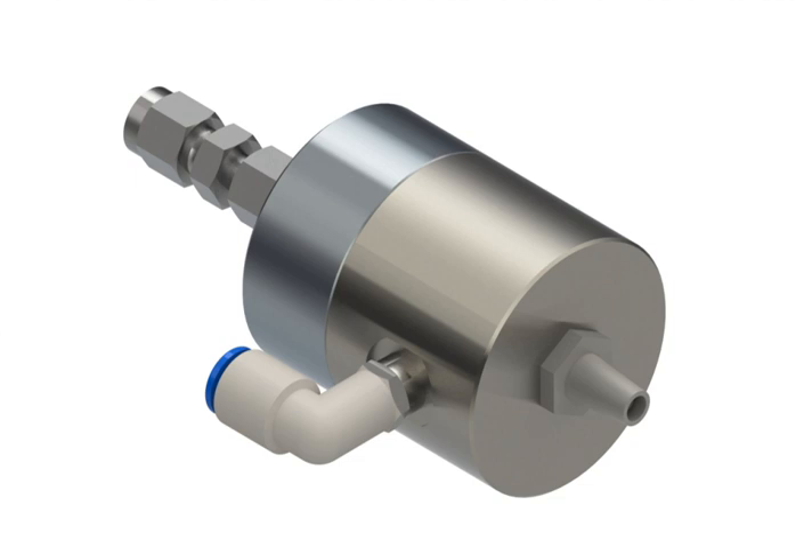Ultrasonic spray pyrolysis is a chemical vapor deposition method utilized in the formation of a variety of materials in thin film or nanoparticle form. Precursor materials are often fabricated through sol-gel methods, and examples include the formation of aqueous silver nitrate, synthesis of zirconia particles, and fabrication of solid oxide fuel cell (SOFC) cathodes. An atomized spray produced from an ultrasonic nozzle is subjected to a heated substrate typically ranging from 300 to 400 degrees C. Due to the high temperatures of the spray chamber, high-temperature ultrasonic nozzle extensions have been designed, with a removable tip hidden under a vortex air shroud (labeled number 2), to protect the body of the nozzle (labeled number 1) that contains temperature-sensitive piezoelectric elements, typically kept outside of the spray chamber or isolated by other means.